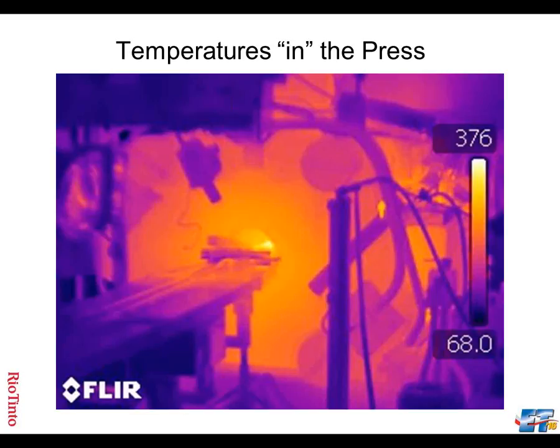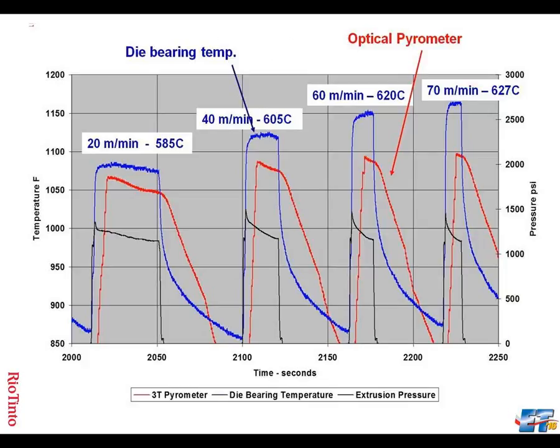We know from measurements, and this has been reported in ET before, that we can reach temperatures as high as 630 Celsius, which is the alloy solidus, the melting point of the alloy. That is 1170 Fahrenheit. And we can draw back dies, which are heat treated at 1100 Fahrenheit. But this just illustrates one thing you can look at.